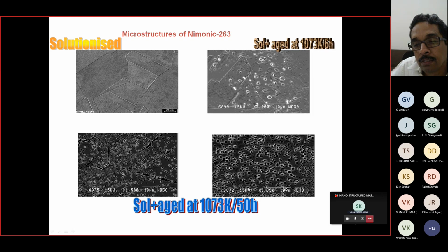See, this is the scale. At a magnification of 3000, this is a length scale of 10 microns. If you see in this 10 micron scale, how many are there? If I count 1, 2, 3, 4, 5, 6, 7, 8, something more than 10 are there. So this is a nano precipitate which is formed in this particular alloy after some heat treatment. I have carried out the heat treatment, which I tried to elaborate here, at this temperature for so many hours, and I am getting this sort of precipitates.